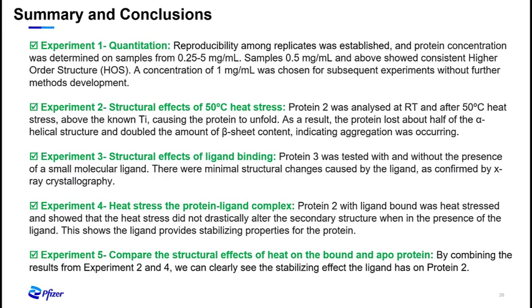In our fourth experiment, we looked at heat stress on a protein ligand complex. Here, we complexed the protein and set it at room temperature and 50 degrees. And it showed that the heat stress did not drastically alter its secondary structure in the presence of the ligand. This shows, again, that the ligand provides stabilizing properties for the protein and protects it. In our last experiment, experiment 5, we compared the structural effects on heat on the bound and apoprotein. We combined the results from experiment 2 and 4, clearly observing the stabilizing effect that the ligand has on protein 2.